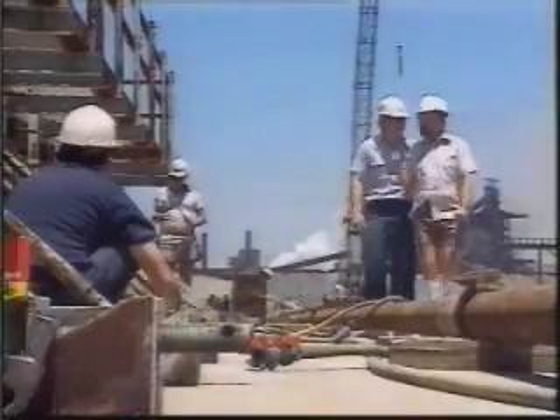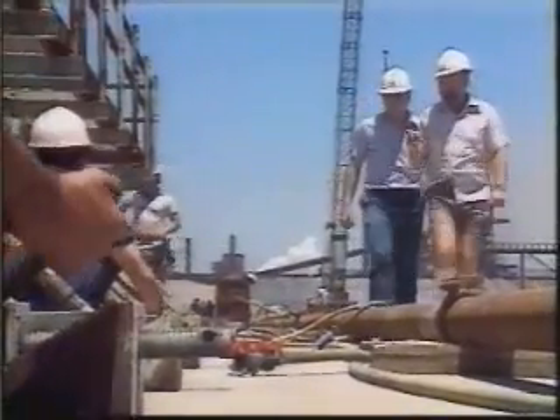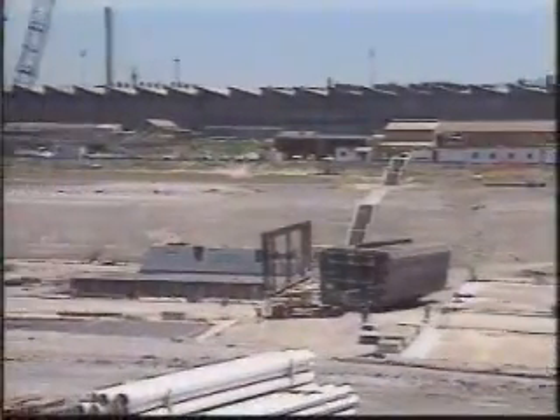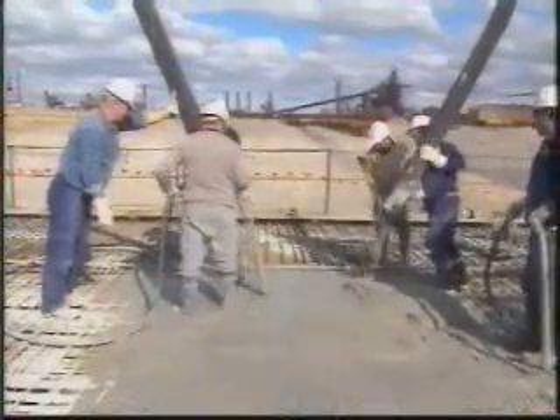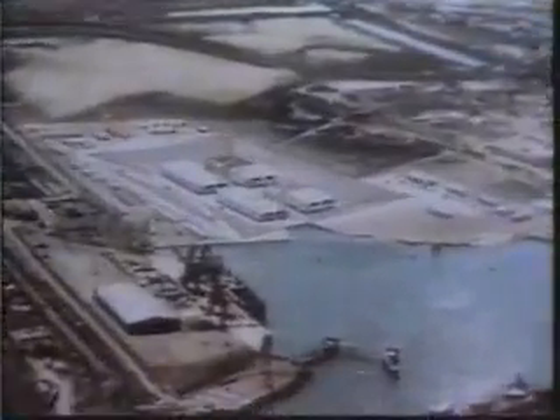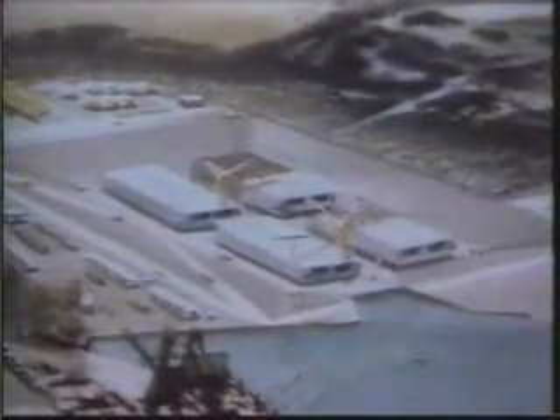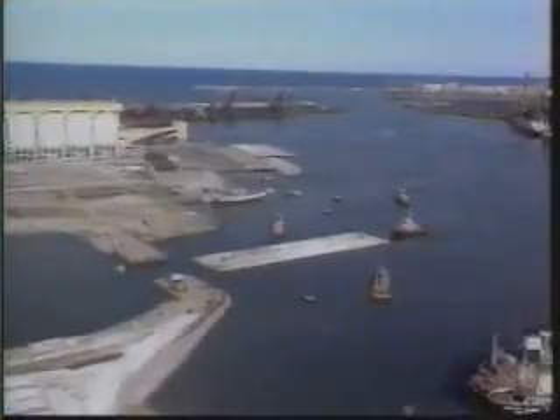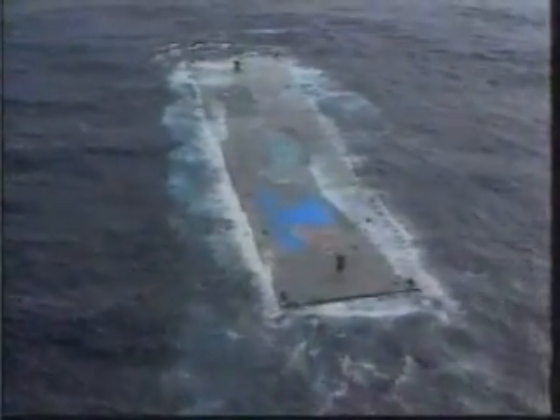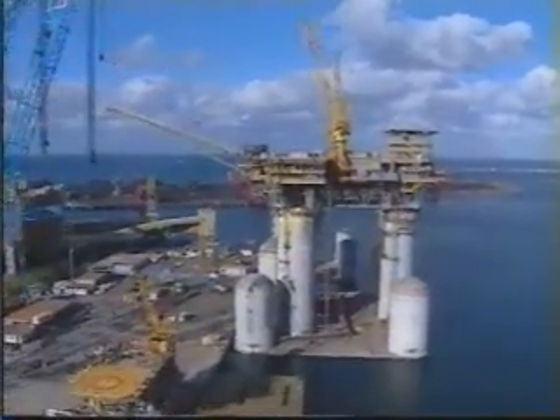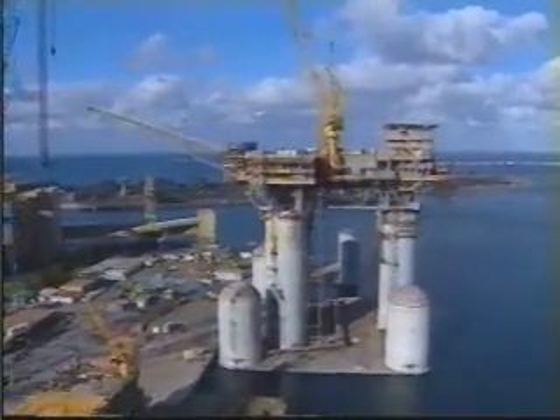An interesting feature of cement containing ground granulated slag is that it produces concrete which has a much greater resistance to sulfate attack and chloride ion penetration compared to ordinary Portland cement. Two specific examples relate to the marine cement developed for use in the Sydney Harbour Tunnel submerged tube concrete tunnel segments and innovative floating oil extraction platforms used in Bass Strait.